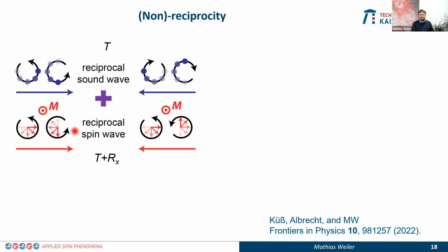And we take spin waves in very thin metals. They're only a few nanometers thick. And that means that the spin waves in these very thin metals have a very low dipolar interaction. They basically only see the exchange interaction. And they're also reciprocal. Okay? So we have reciprocal sound waves and reciprocal spin waves typically.